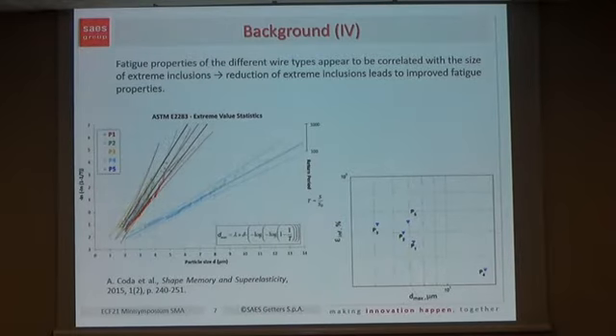We analyzed a lot of failed wires after different fatigue testing by using the rotary beam test, and we analyzed the fracture surface, and we at the end found that the inclusions at the crack tip follow typical Gumbel distributions. The populations in different materials follow different Gumbel distribution functions. And in this way, we were able to distinguish the effects of different inclusion types, size and distribution in different commercially available materials. On the other side, looking at the extreme inclusions that we use in this approach, also following the recommendation of ASTM